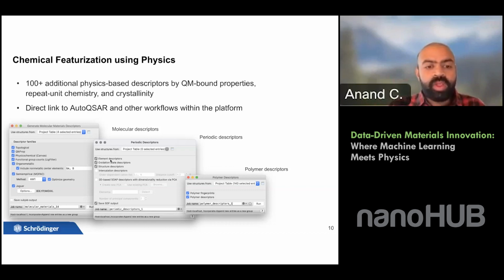For example, all these element descriptors, oxidation state descriptors, and structure descriptors are Matminer based descriptors that we've built in on the backend, and we can go directly from a CIF file to the Matminer descriptors. We have some intercalation descriptors that are specific to lithium-ion cathode materials that take into account the environment around a lithium-ion in a solid-state system. These descriptors can be used, for example, for training a machine learning model for lithium-ion cathode materials.